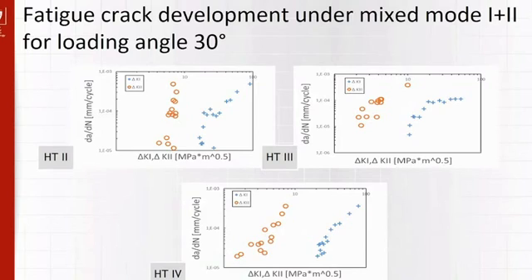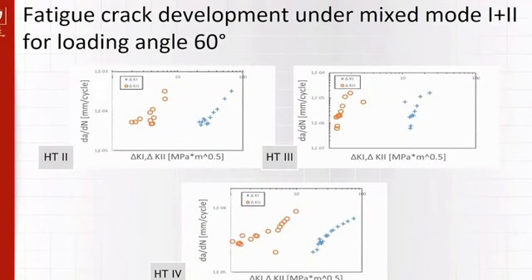As you can see in this case, for the loading angle of 30 degrees there is no visible difference, but when we go to the loading angle of 60 degrees, you can see that the HT4 heat treatment has a noticeably lower crack growth speed.